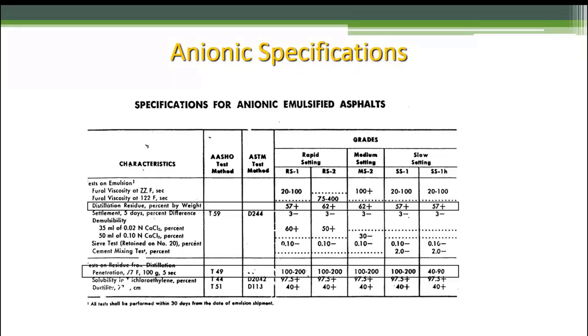Well, remember, you're only starting with 57% asphalt. So my shot rate, and what you'll see on plan sheets typically is a recommendation for tack rate, and that's a minimum. And it'll say 0.06 gallons per square yard, for example. Well, that's six hundredths of a gallon per square yard of pavement. That's based on this undiluted shot rate. In other words, it's already worked in that it's 57% asphalt, basically. If I dilute it further than that before I shoot it, I've got to increase my shot rate.